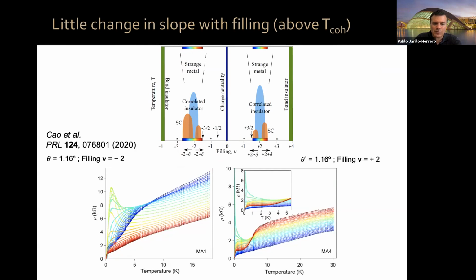So at low temperatures, you can have superconductivity, a metal-insulator transition, all kinds of correlated insulator behavior. But once you go above a certain coherence temperature, your behavior is linear, and the slope is very weakly dependent on doping. This is data for a 1.16 degree device around 2 holes per moiré unit cell. This is data for a different 1.16 degree device. It's just a coincidence that it's the same angle, but it's a different device, for data around 2 electrons per moiré unit cell, and you can see how linear, and how weakly dependent the slope can be in the system around this range.